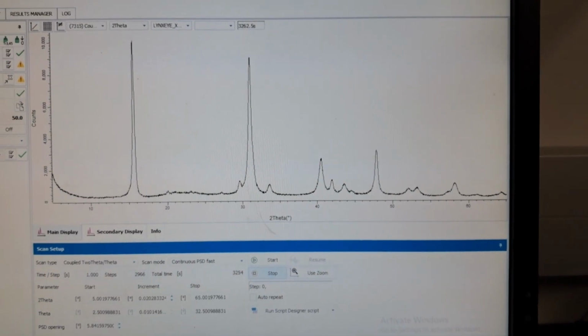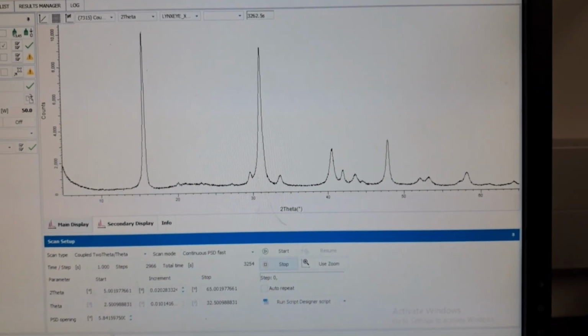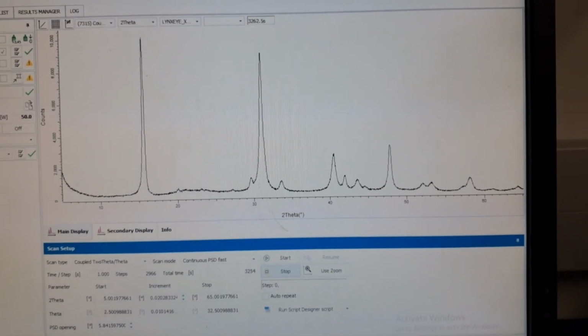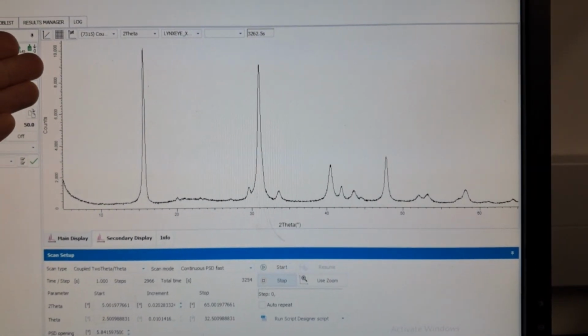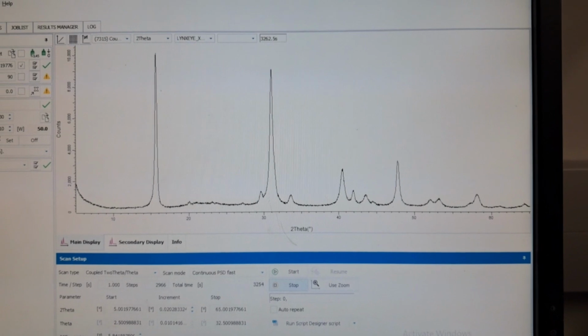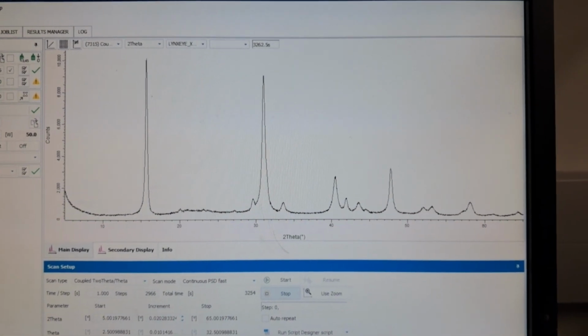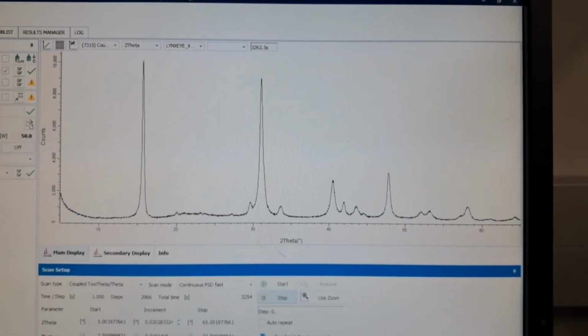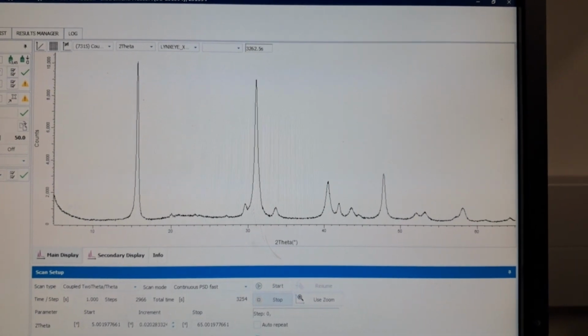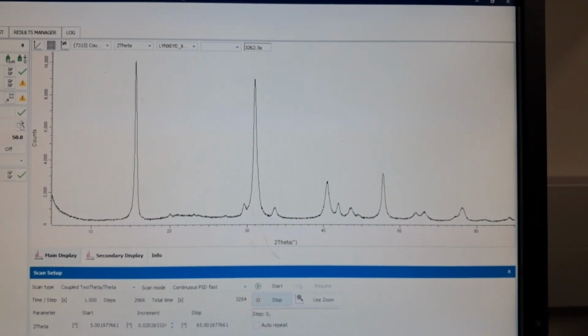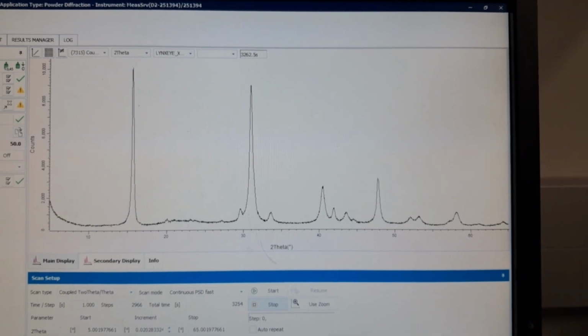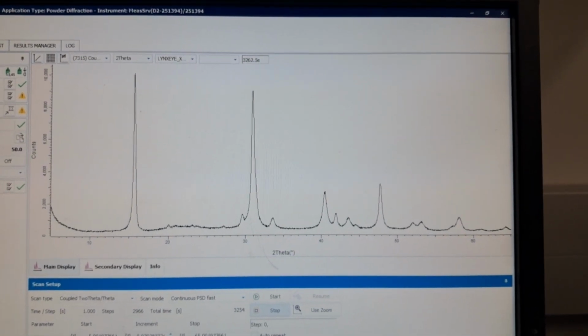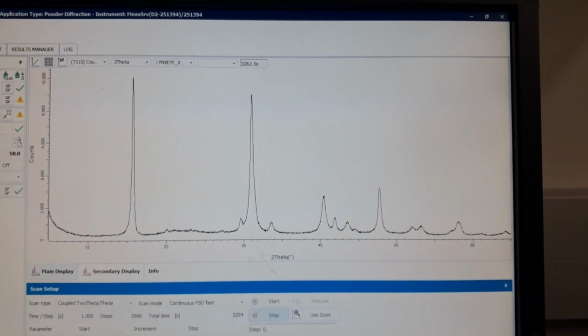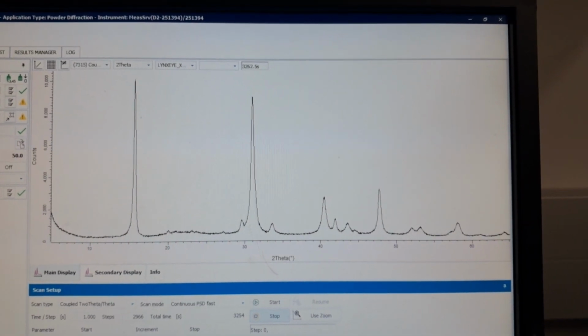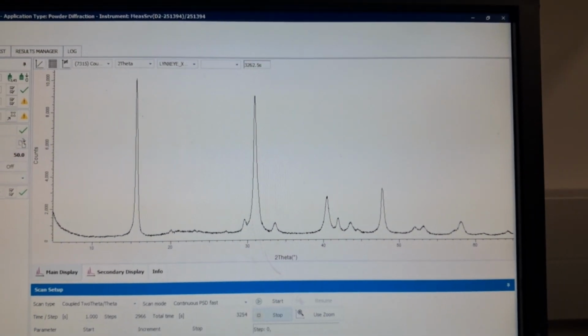The second ground run has concluded, and if you recall what the intensity was for the first one, we're seeing substantially larger peaks and the same quantity of peaks. So for this particular material, it appears that using the larger quantity definitely will lead to a cleaner pattern that should still be able to be solved by Rietveld or Le Bail just as easily or slightly better than the first one.